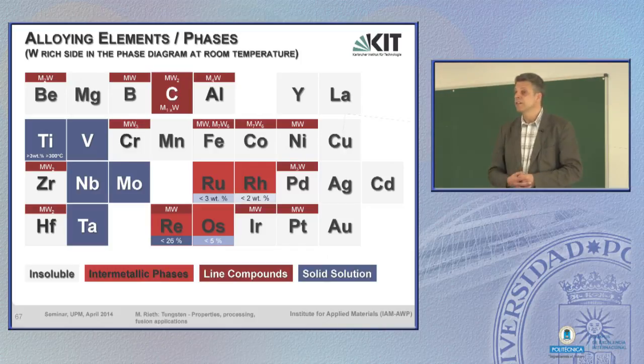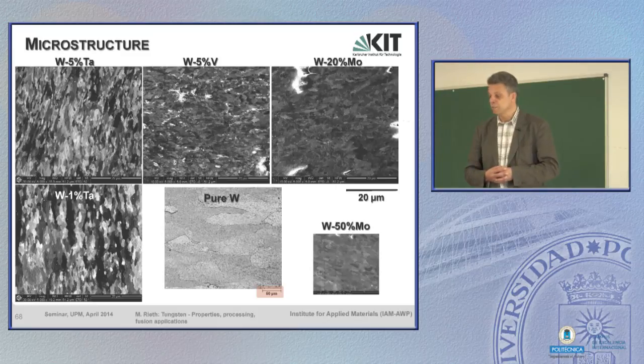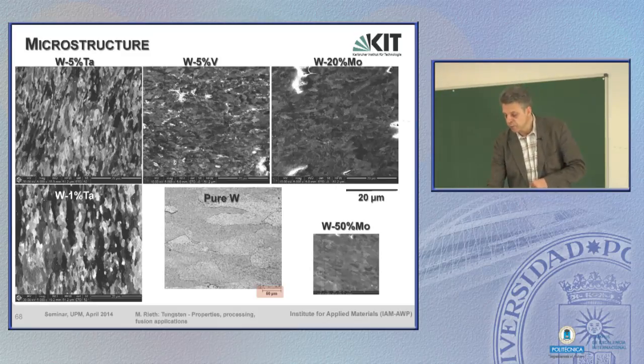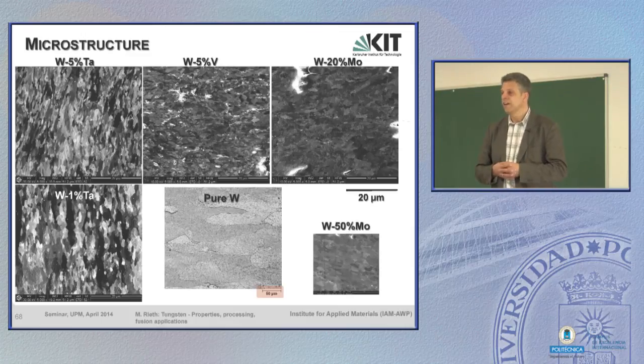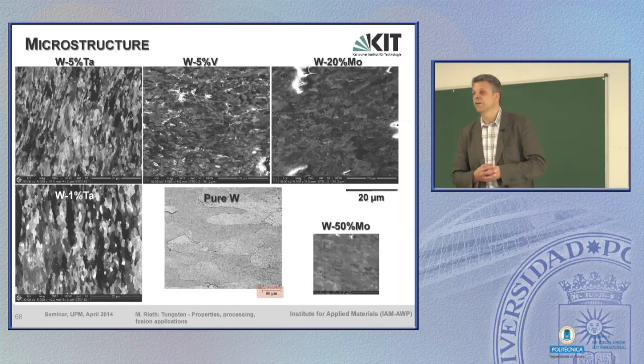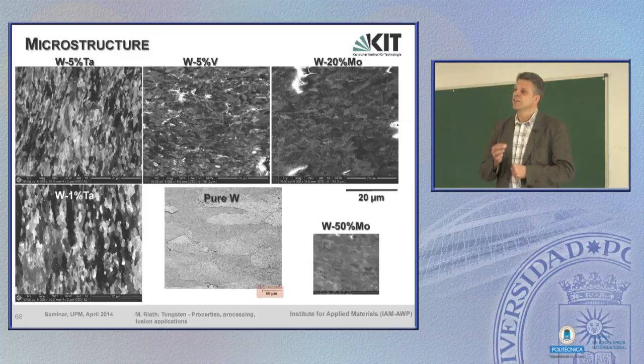We have produced this material, or at least Plansee, the manufacturer, has produced this material, and you see immediately the difference in the microstructure. This is pure tungsten, and here is the measure, 50 micrometers, whereas here we have to measure with 20 micrometers. You see one effect immediately. The addition of solid solutes produces a much finer grain.